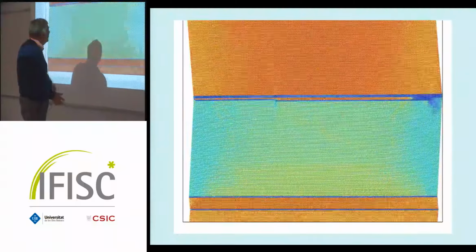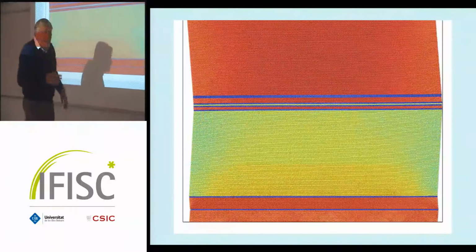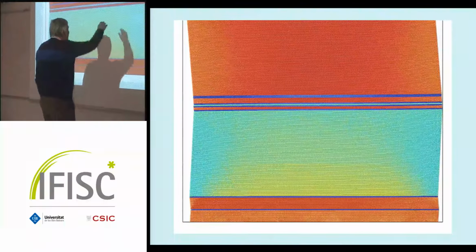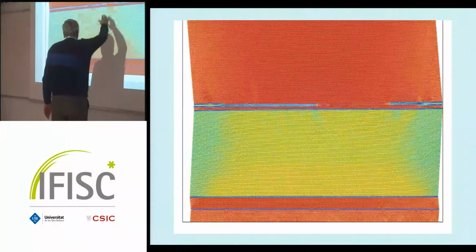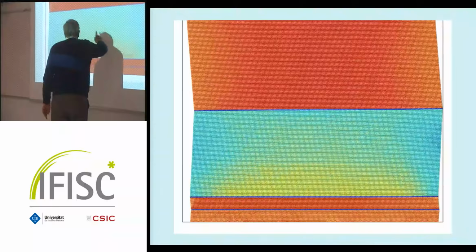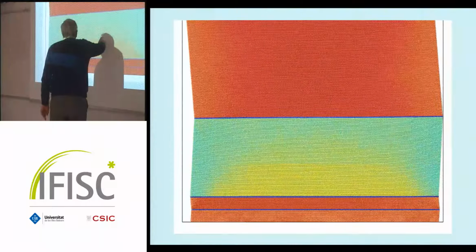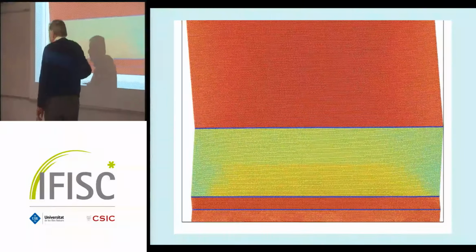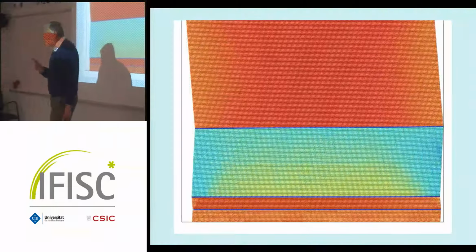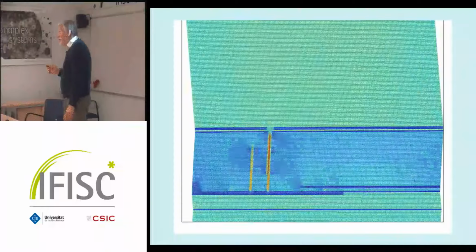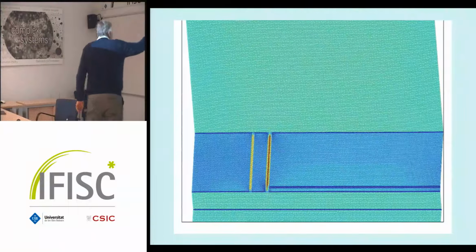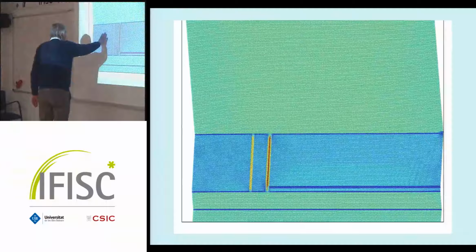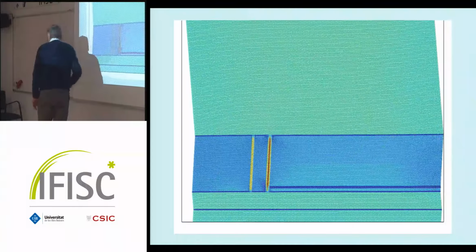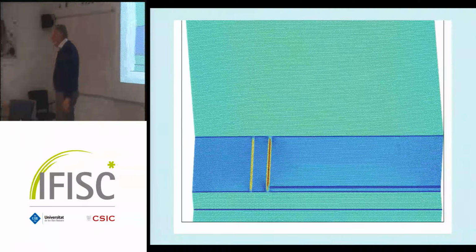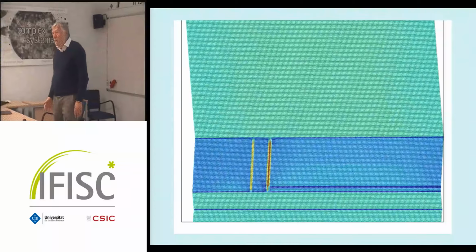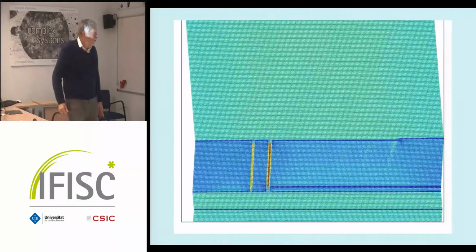You can see, whatever there is the kink configuration, and that kink configuration will completely disappear here because the red has to win over the green. That's the right orientation, that's the wrong orientation, and these ones are the interface. But the important thing is that the interface which is taken out here is the unstable one. So you have here on the top, this material here is stable. This material is not quite stable, but all changes are done by the interface. So you can produce this interface as much as you like. Right?